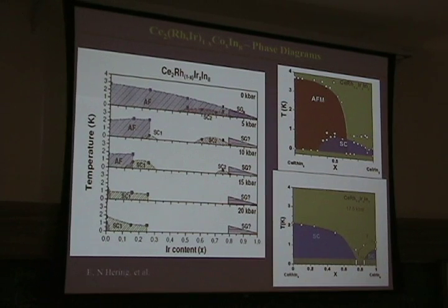So going to the bilayer version seems to suppress the occurrence of superconductivity. You're reducing the energy scale, and also the range where you find that superconductivity. So higher dimensionality seems to compromise the occurrence of Heavy-Fermion superconductivity in these materials.